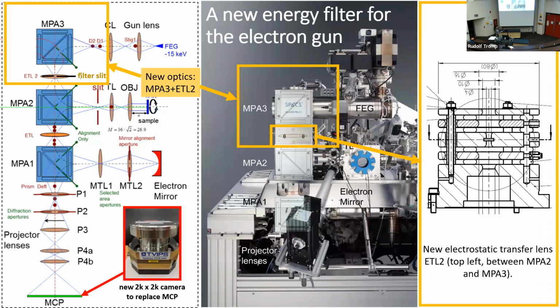The last 2 years, I've worked on building, so here's the electron gun, a cold field emission gun, which has a width, depending on where you measure it, of a quarter EV to an EV or so. I'll show it in a second. And we could do better by putting an energy filter in the gun.